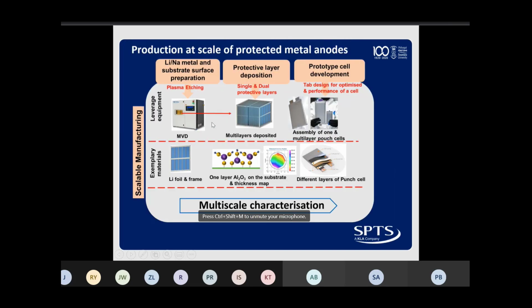We do this through, of course, we look at scale up. So what we do, we deposit such layers through molecular vapor deposition. These are instruments that are commercially available, and they are constantly used in the semiconducting industry. But now, in collaboration with the company that manufactures them, we are modifying them for energy storage work. And we use this type of system because we can have batch production, so we can actually reach all the target levels of production of anodes per year. And also the advantage is that we can directly coat on both sides of the lithium foil or the sodium foil, and therefore we can move on for the direct production of, for instance, pouch cells.